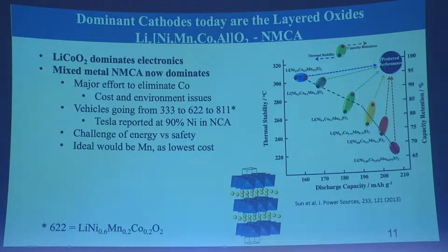So it's what I said originally about John's work at Oxford. All these oxides, when the lithium's out, the +4 oxidation state, the metastable, in principle, they should evolve oxygen at room temperature. But it's kinetics. So this is just telling you what temperature these materials are going to lose oxygen. And you can see from the axis at the bottom, we want high energy density, which means we want to be at the right-hand side. If we're at the right-hand side, then we have the lowest thermal stability.